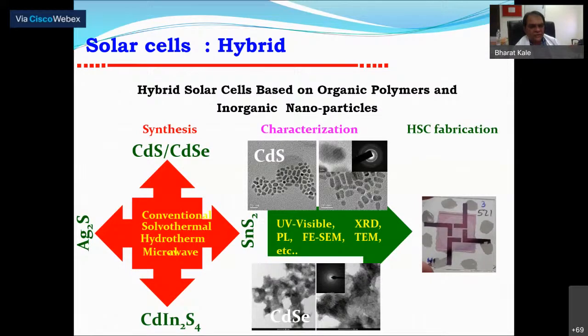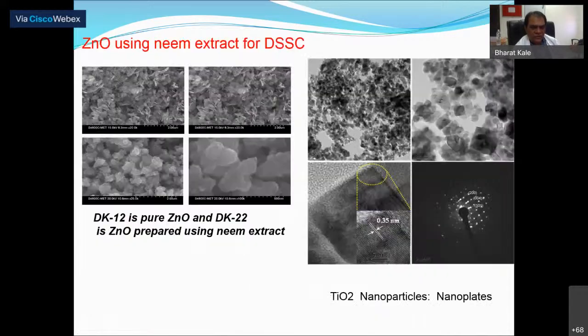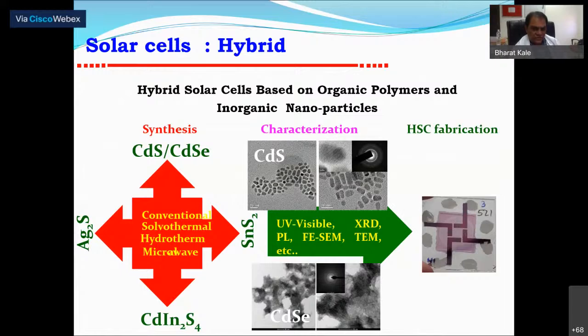This is a hybrid solar cell, based on organic polymers and nanoparticles, that we are making. Very basic things we did, like we have used cadmium sulfide, cadmium selenide, then Ag2S, SnS2, and CdIn2S4. All these materials we have used for making these thin film solar cells. But still, we have the issue of efficiency. We are not going beyond 3 to 4%. So we need more experience on fabrication. We have to do many experiments on fabrication and solve the problems.